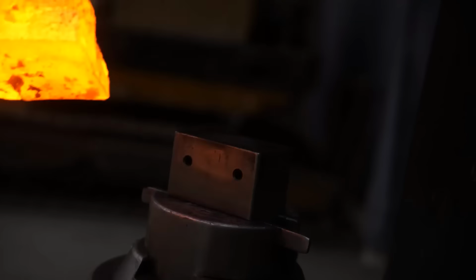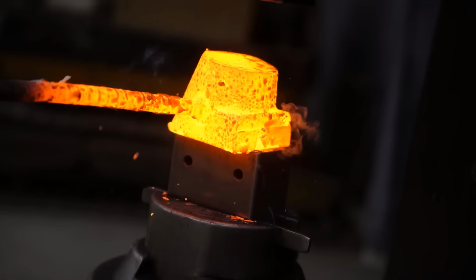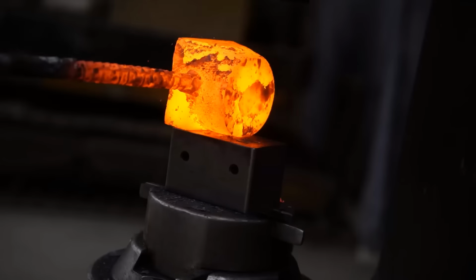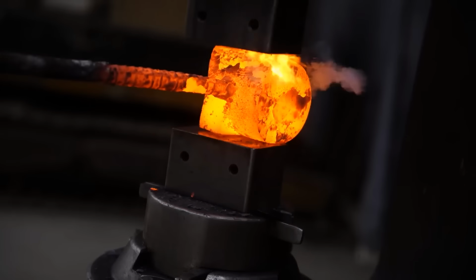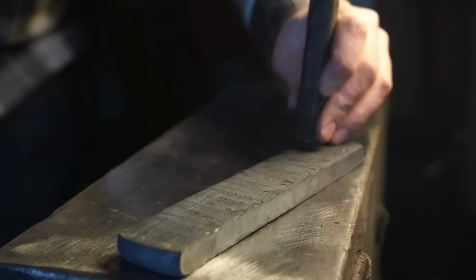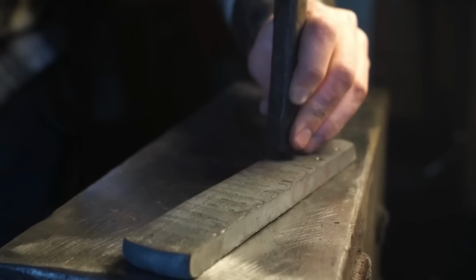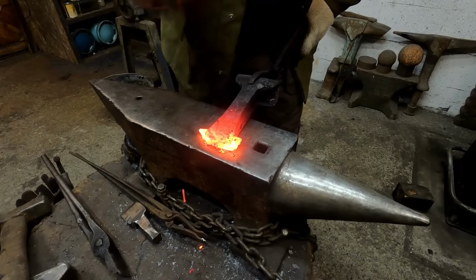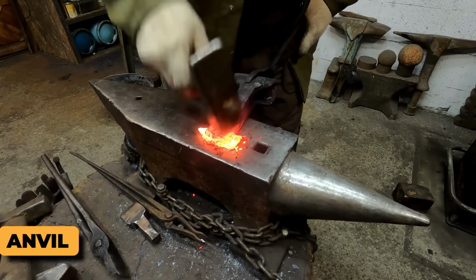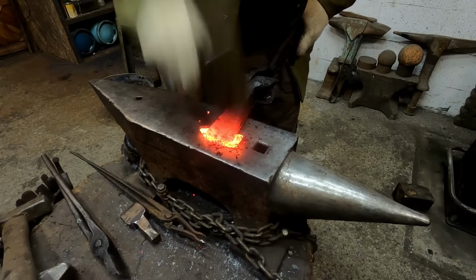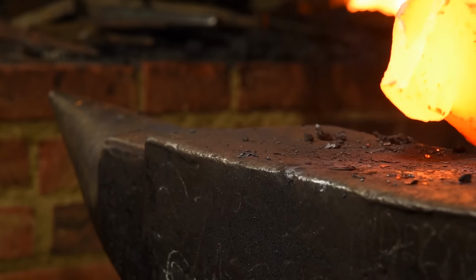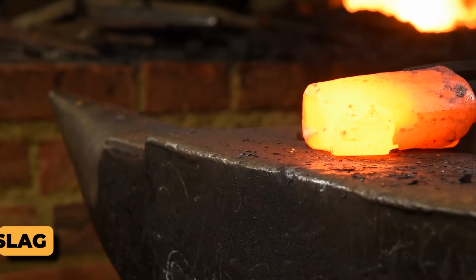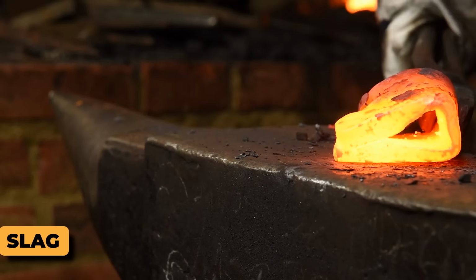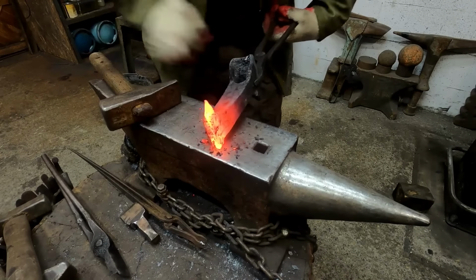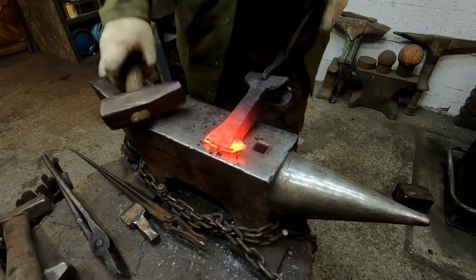Pulling a 25-pound iron bloom out of the furnace was like catching a burning meteor with your bare hands, except you had seconds to act. If you waited too long, the bloom cooled into a brick, harder than regret. So the blacksmiths slammed it onto an anvil, a huge stone or iron block, and started hammering like their lives depended on it, because they sort of did. Every blow forced out slag, those glassy impurities that made iron brittle. If you left too much inside, the axe would shatter the first time it hit a shield.